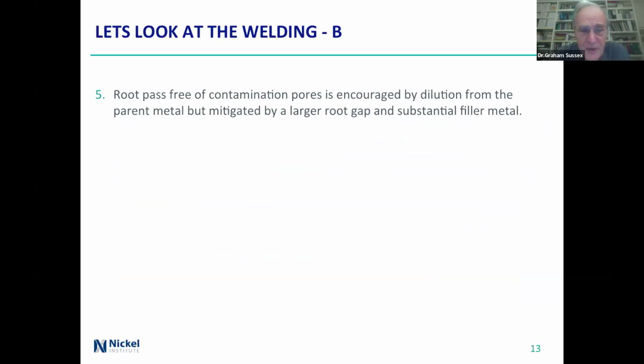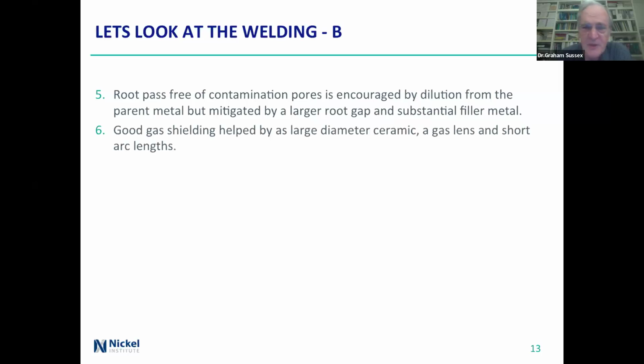The root pass has got to be free of contamination, otherwise you wind up with poor porosity there. And that's going to be encouraged by dilution from the parent metal, because you're putting in a designed filler and you really don't want more parent metal coming in than normal. So you say, let's make it a slightly larger root gap so you don't get so much parent metal coming in, or increase the amount of filler metal you're putting in. So that's really about getting the actual root level having decent corrosion resistance, decent properties.